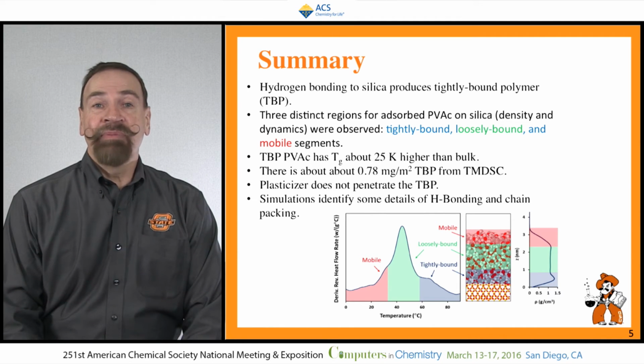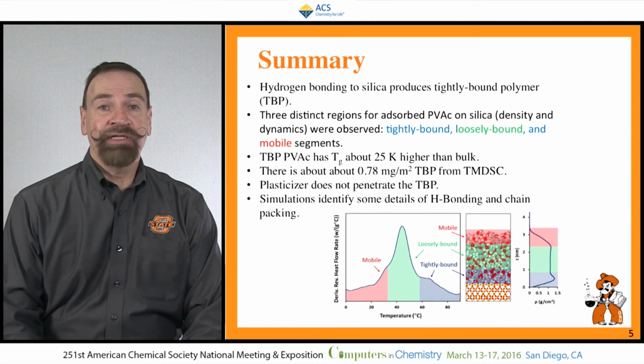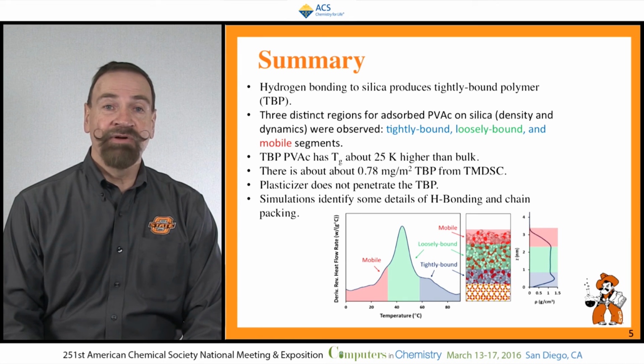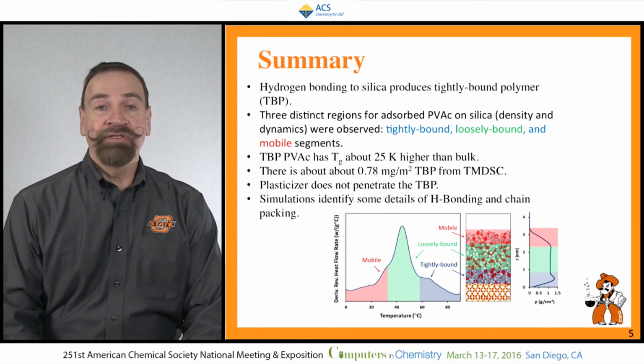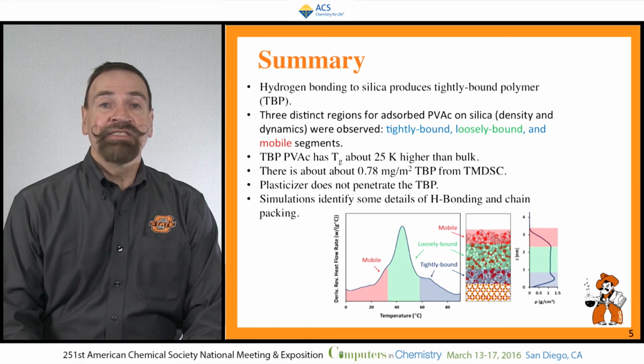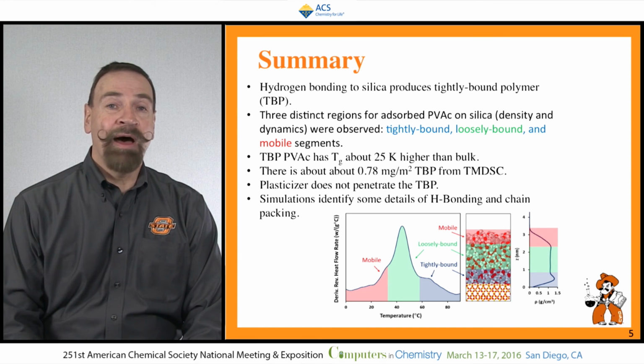This tightly bound polymer also has some interesting properties. In particular, if you try to put plasticizer in to lower the glass transition of the tightly bound polymer, it won't work because it doesn't go in. And we have used computer simulations to identify some of the details of the hydrogen bonding and also the chain packing in those systems.